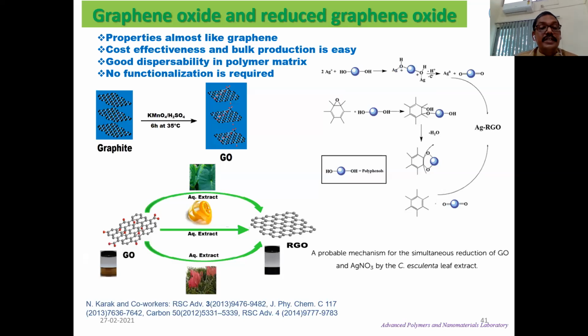We have also used graphene oxide and reduced graphene oxide. Now, graphene oxide is obtained same as Hummer's method, but to get the reduced graphene oxide, we have used our own strategy, where we use bio-based material across different phytoextracts, and these, in presence of a suitable catalyst, a metal ion catalyst, are able to reduce this graphene oxide within 3 to 10 minutes with a high yield. Normal conventional systems need more than an hour. Using this same strategy, you can also obtain different nano hybrids with other materials using the same phytoextract.